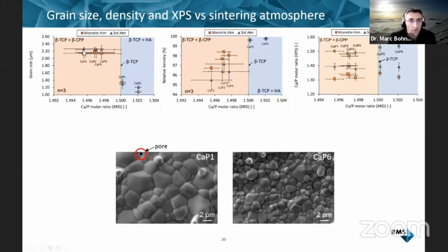The result I showed before are these triangles, and now these squares are samples that were started with the same powder but sintered in a phosphor-rich atmosphere. So what we did was to co-sinter calcium hydrogen phosphate and beta-tricalcium phosphate. And the calcium hydrogen phosphate releases a lot of phosphor species and basically saturates the atmosphere. So this prevented the beta-TCP from losing phosphor species. And we see that this has an effect on the grain size, on the relative density.